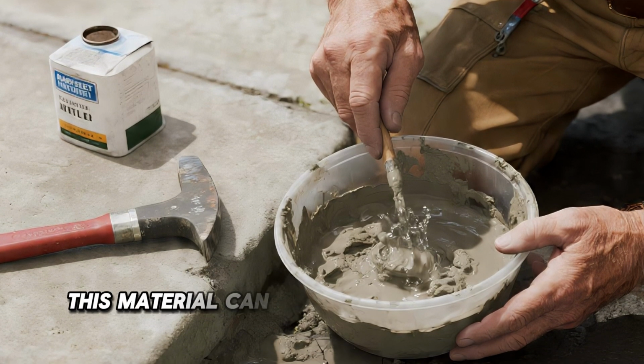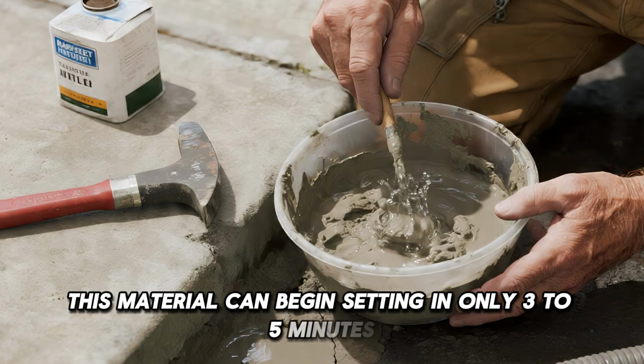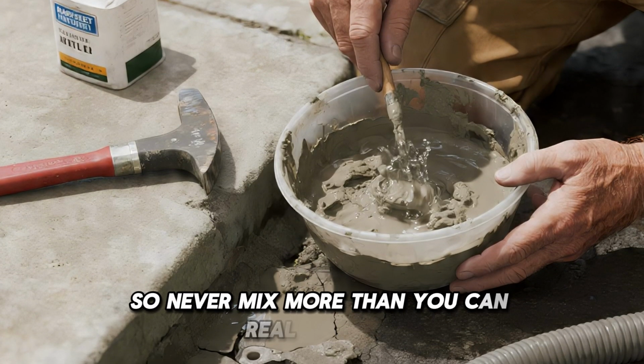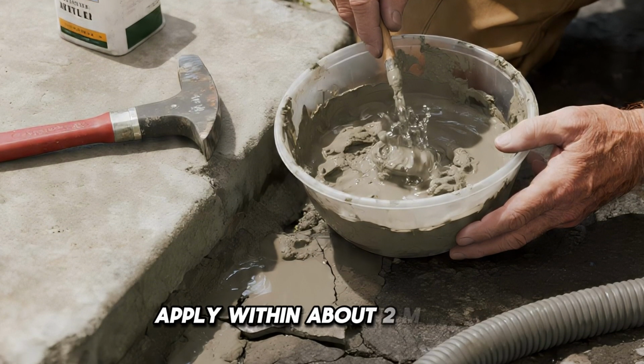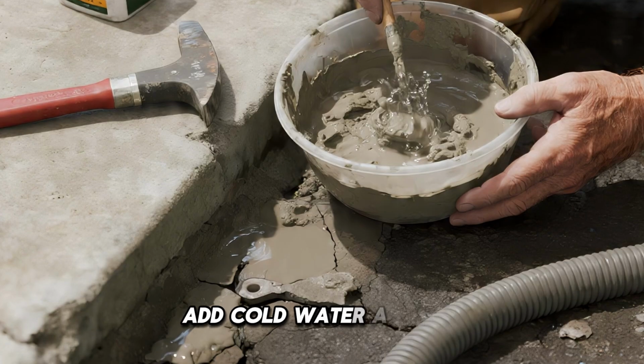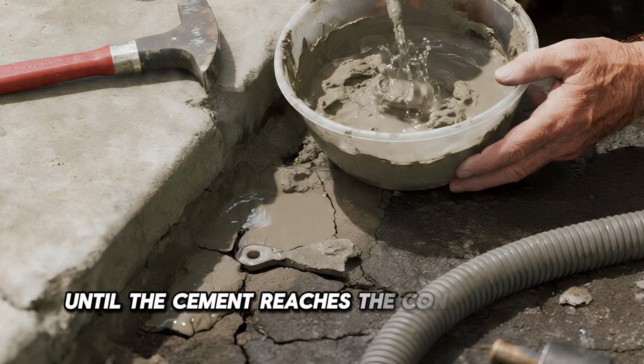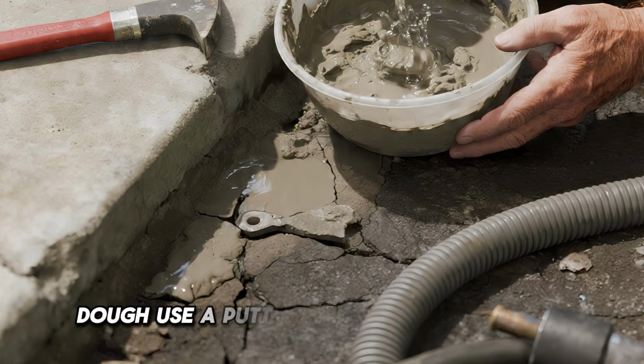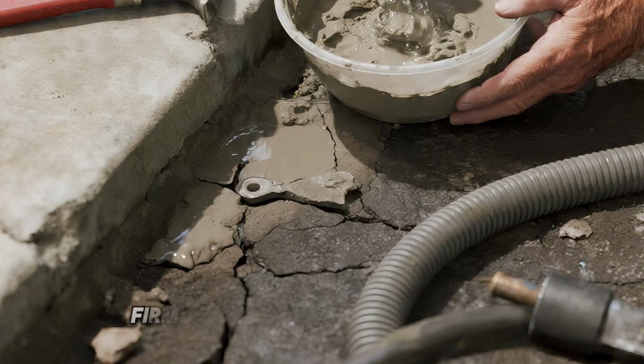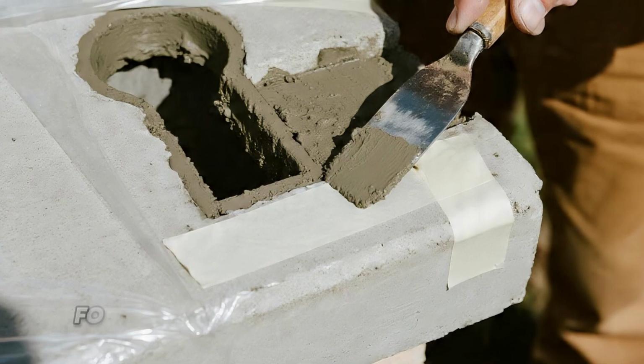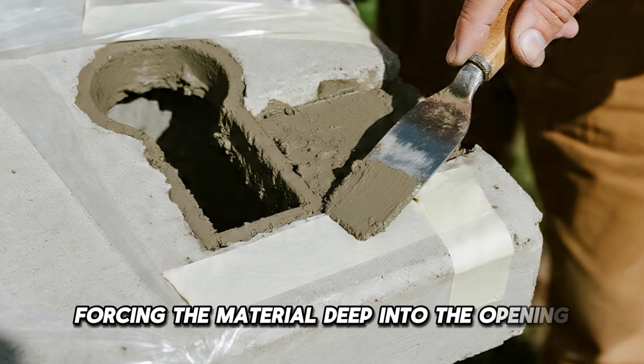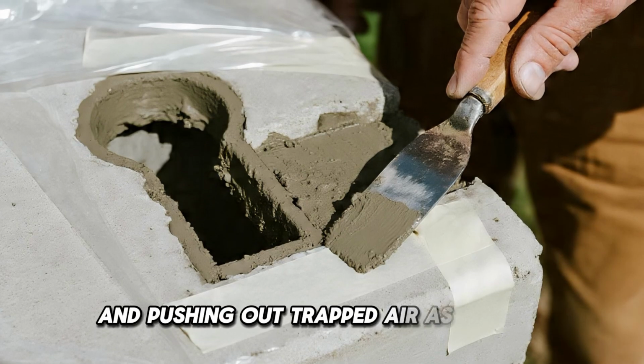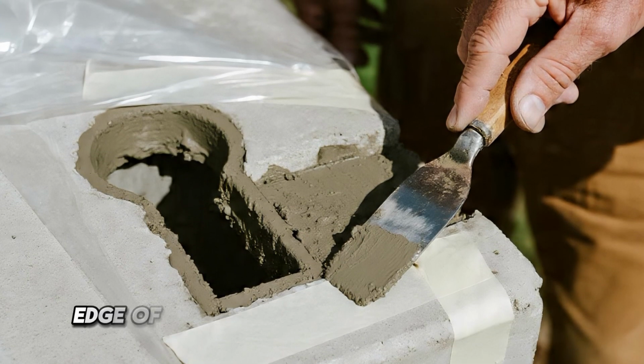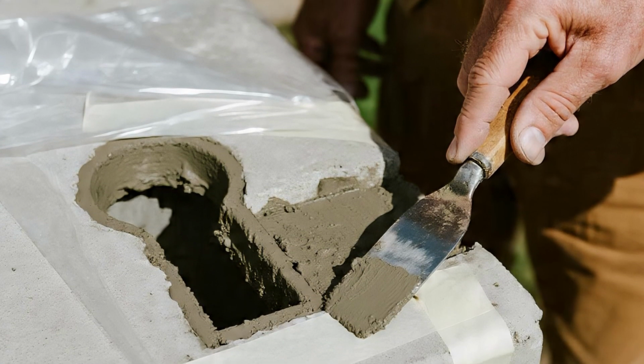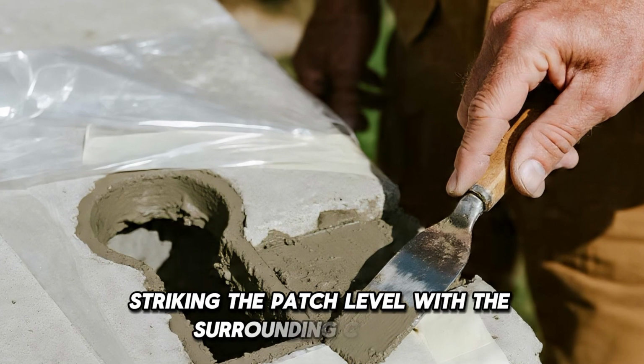This material can begin setting in only 3 to 5 minutes, so never mix more than you can realistically apply within about 2 minutes. Add cold water and mix until the cement reaches the consistency of a stiff dough. Use a putty knife to press the paste firmly into the prepared keyhole, forcing the material deep into the opening and pushing out trapped air as you go. Then run the flat edge of the putty knife across the surface, striking the patch level with the surrounding concrete.